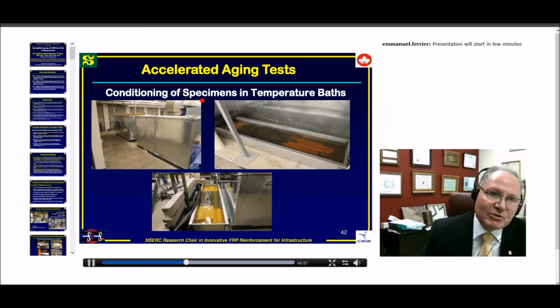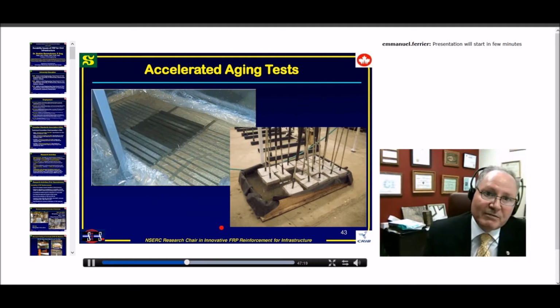So here I'm showing conditioning of specimens in temperature baths. This is all of them. It's not really under load, because if we have load, we will have a synergistic effect, and that could also be investigated. But mostly we are doing this without load, and we limit the load, of course, to the minimum so as not to induce any other problem.